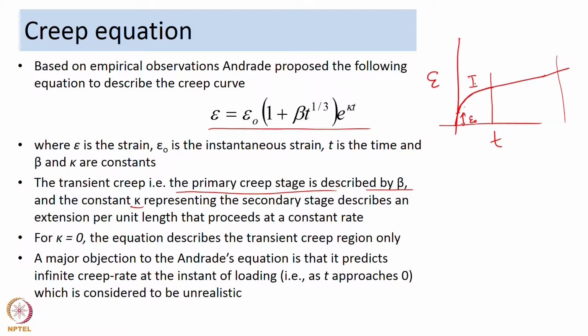So, while this was one of the earliest equations to describe creep, there were some objections raised to Andrade's equation, and one of the major objections is that it predicts an infinite creep rate at the instant of loading, that is when t is very small or when t approaches 0, the creep rate approaches a value of infinity, which is considered to be unrealistic.